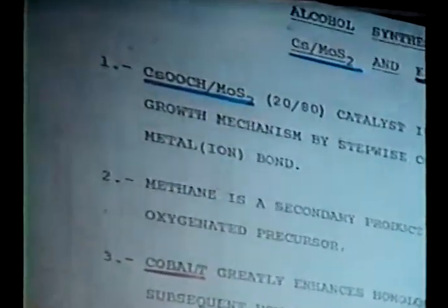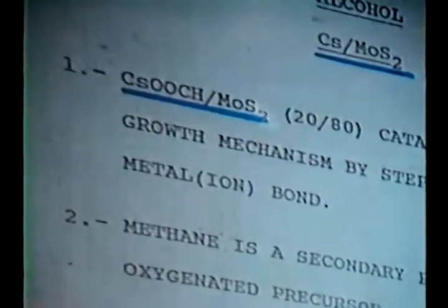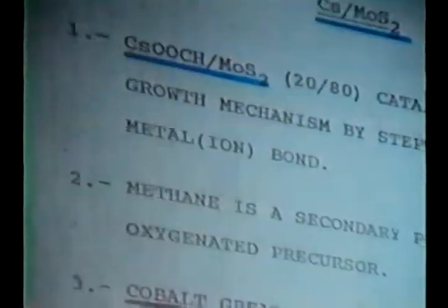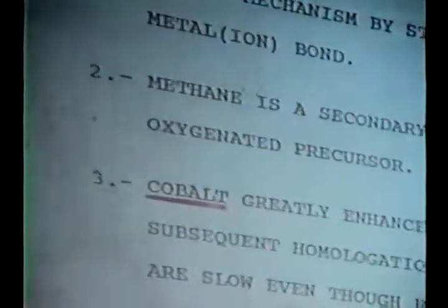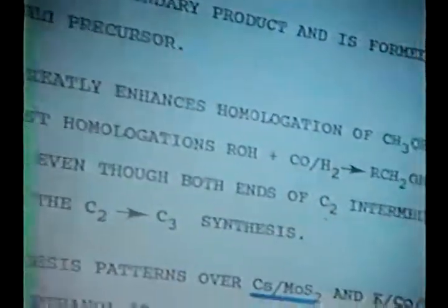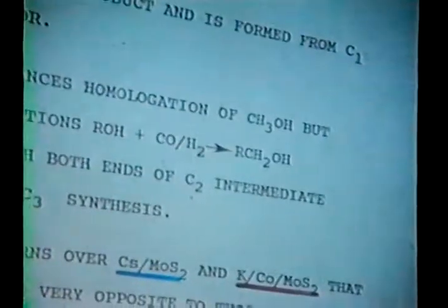Now, I want to take a few minutes extra to compare the system with the copper-zinc catalyst. And before doing that, this is the classical chain growth mechanism, CO insertion into the alkyl metal bond. Methane is a secondary product. Cobalt greatly enhances that C1 to C2 step, and the synthesis patterns over those two catalysts are similar and dissimilar in the sense that I talked about before.